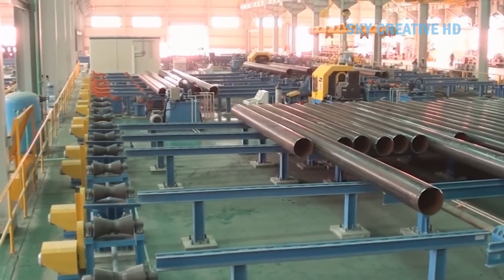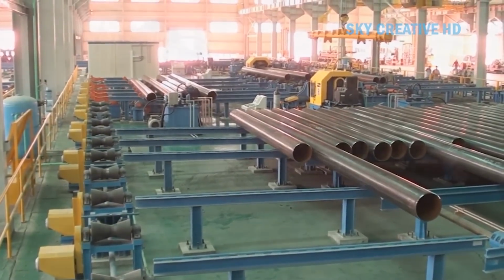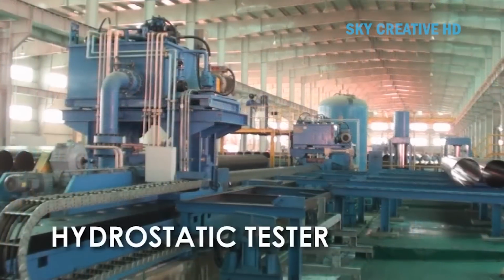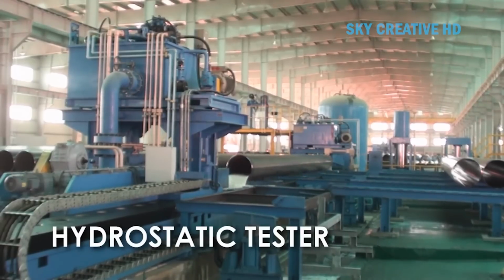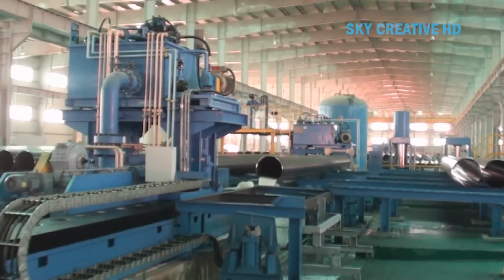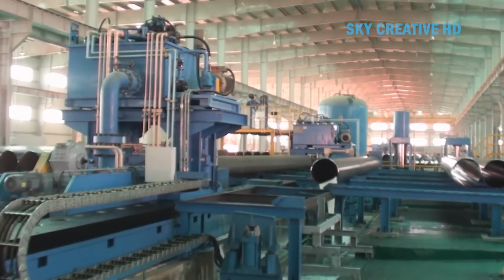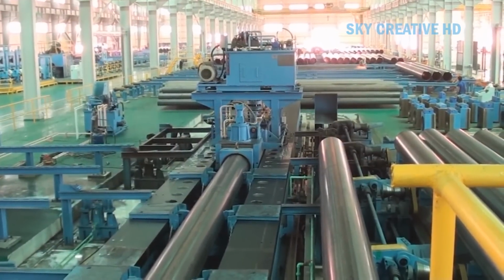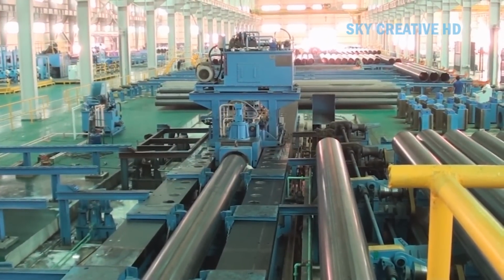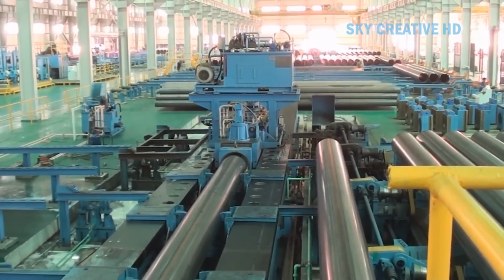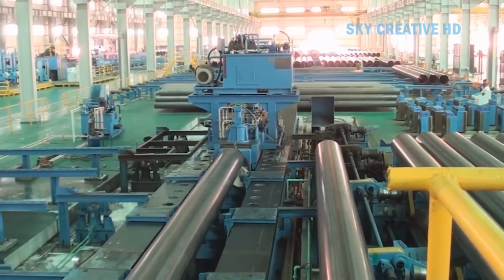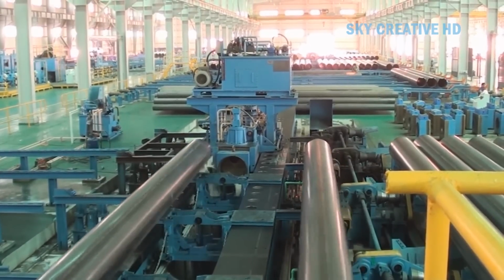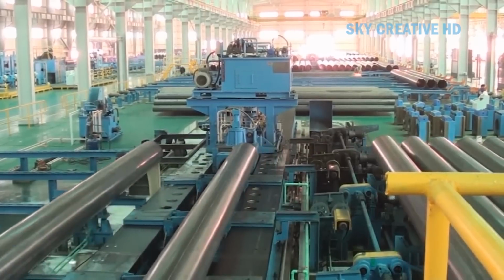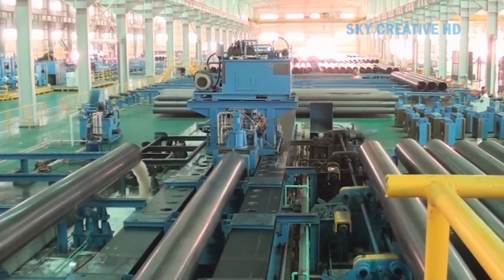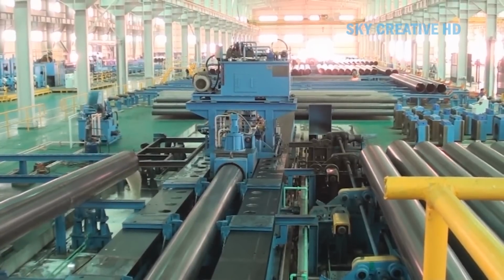The scrap rate decreased from 5% to only 1% thanks to the ability to strictly control each stage, from forming to welding and cooling. The system allows quick conversion between different pipe configurations within just 15 minutes. Previously, it took up to 2 hours. Square, rectangular, and round pipes can be produced with sizes from 25 mm to 150 mm, meeting the diverse needs of customers. Dimensional accuracy reaches plus or minus 0.05 mm, far exceeding standard requirements. The weld seam is smooth, without defects, meeting international standards such as ASTM and ISO.